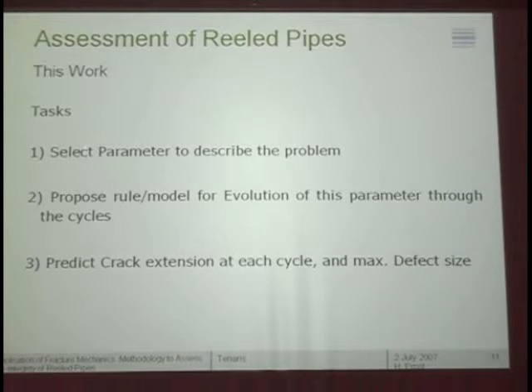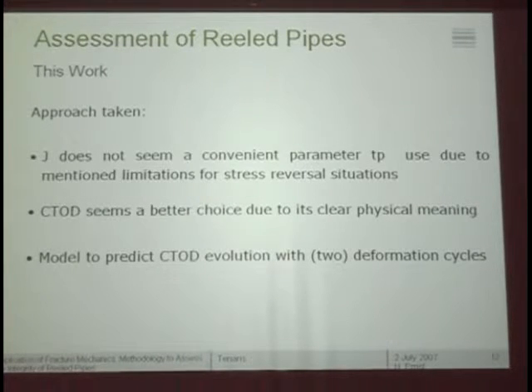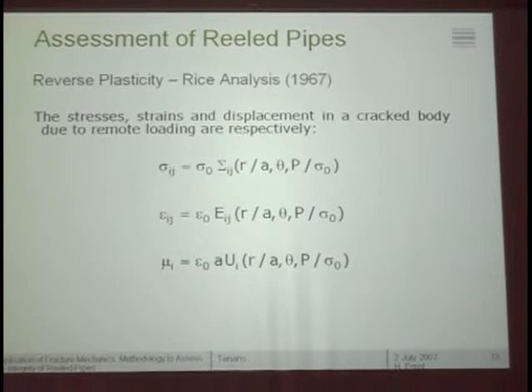The task then that we need to go through is basically to select a parameter to describe the problem, propose a rule or model for the evolution of these parameters through the cycles, and then of course predict the crack extension at each cycle and determine the maximum defect size. In this approach that we took here, we feel that J does not seem very convenient because of the limitations that we use. So we are focusing on what we call a CTOD approach, because it seems to be a better choice due to its clear physical meaning upon unloading criteria. So at least we need a model to predict the evolution of the CTOD with deformation cycles too in principle, but we will see how we can add several ones to this step.